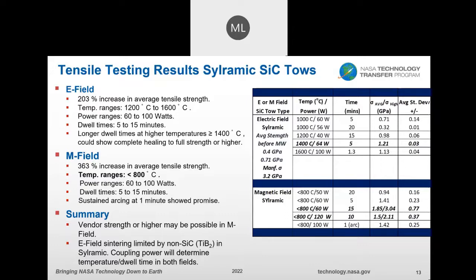And the reason it's less than 800 degrees C, and I'm not giving you an actual temperature, is because the pyrometer that we were using in this system measures temperatures from 800 to 2000 degrees C. So we noticed that it was getting hot, and so we kept doing the test from 60 to 100 watts and from 5 to 15 minutes. And in one case, we were able to sustain an arc for 1 minute, and it showed some promise.